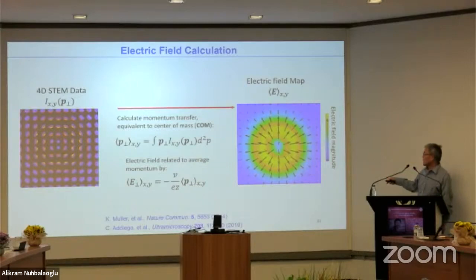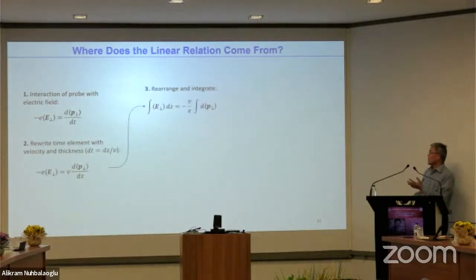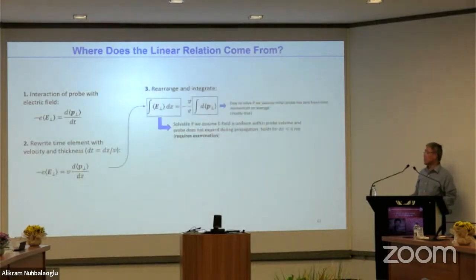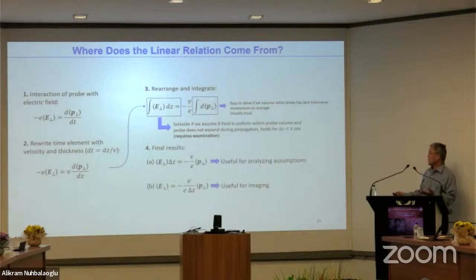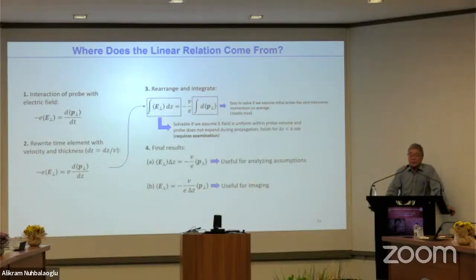Okay. So from this electric field from the 4D scan, you can see that for strontium titanate you have cubic symmetry. It's all like a radial symmetry. That's good. With this field determined, you can get charge information. That will come on the next slide. But there's a question: in which kind of scenario will this interpretation be valid? In other words, what is the limitation of linearity?